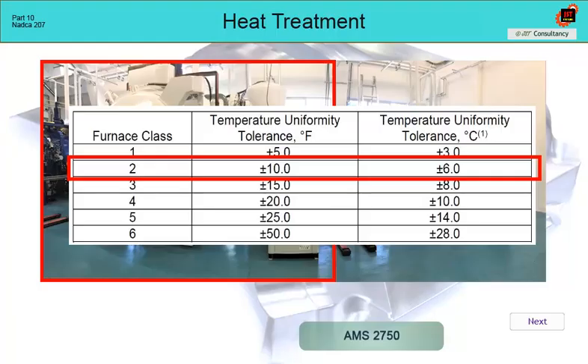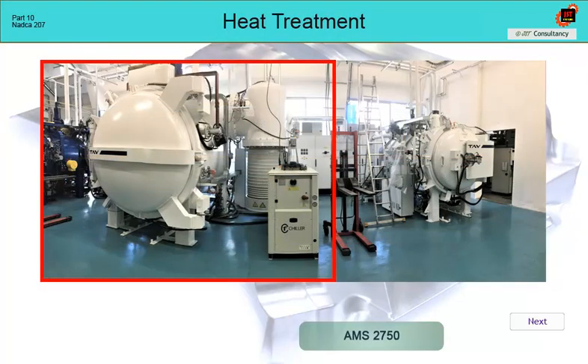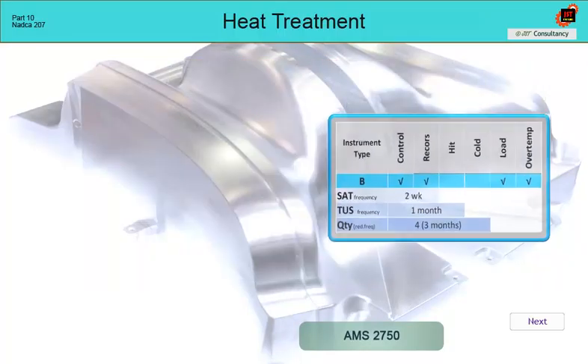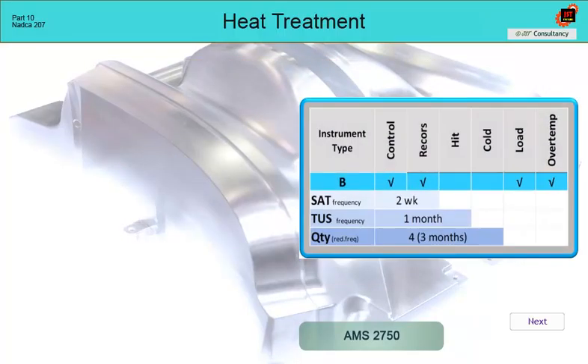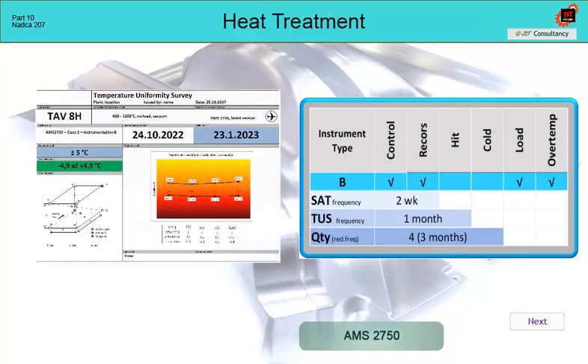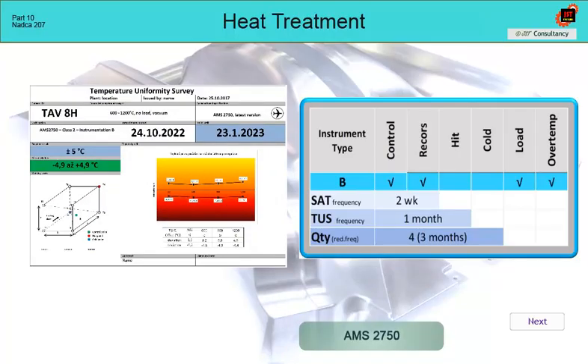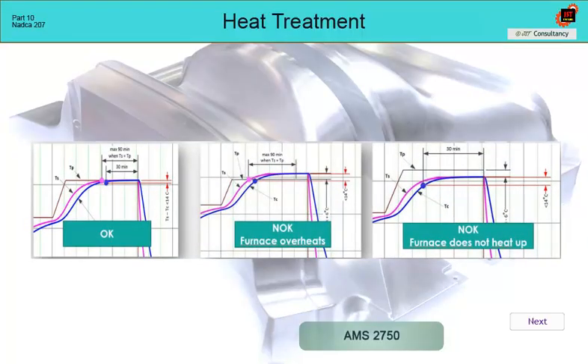Of course, the tool shop does not need to know anything about the furnace temperature control system. But if it audits the heat treatment plant, it should demand compliance with the periodicity of calibrations according to the standard. It is in the toolmaker's interest that the recorded temperatures correspond to reality. From the records, it should be seen at first glance that the programmed temperature of the furnace is in agreement with the actual temperature on the furnace control thermocouple. The furnace may not underheat, but neither overheat.